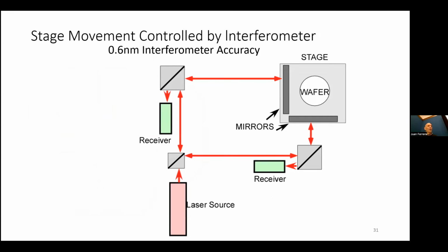So how do we move from one field to the other field and have everything match up in between the fields? That's because we have a stage that's controlled, or feedback is given, by a laser interferometer that measures very precisely and accurately, down to about 0.6 nanometers, the position of the mirrors that are on the stage that hold your wafer, your piece. So that means we know really, really accurately where we are in terms of the mirrors. Now, if you stick a cold wafer on a hot stage, you're going to get thermal expansion and things won't work so well.